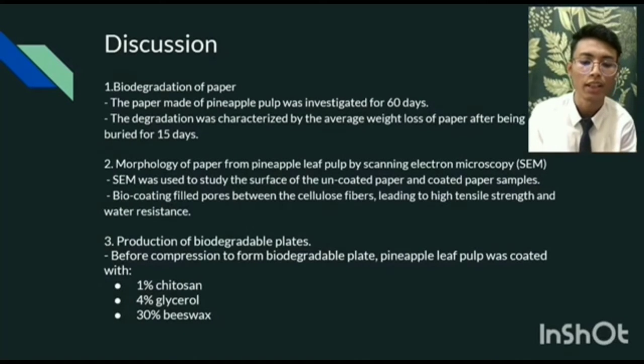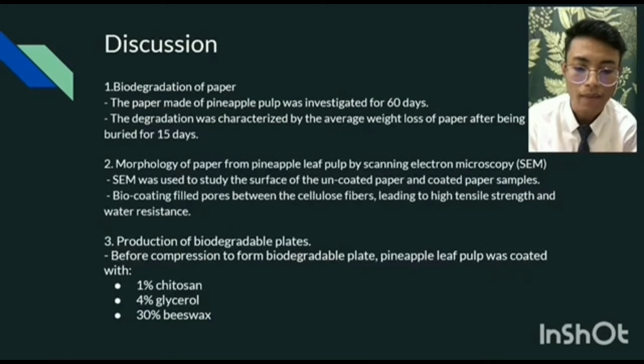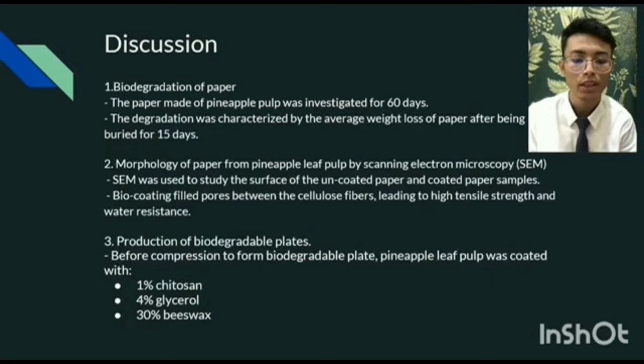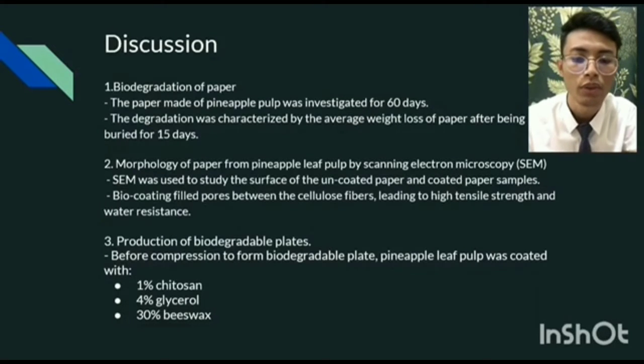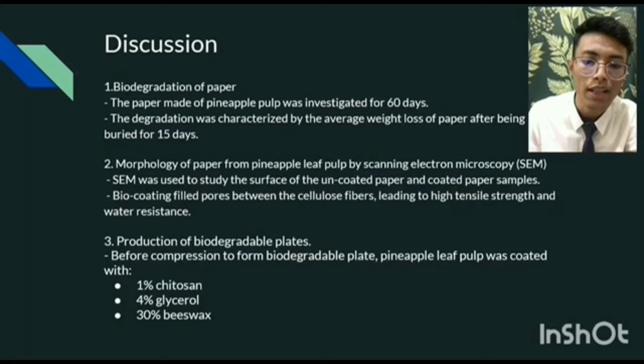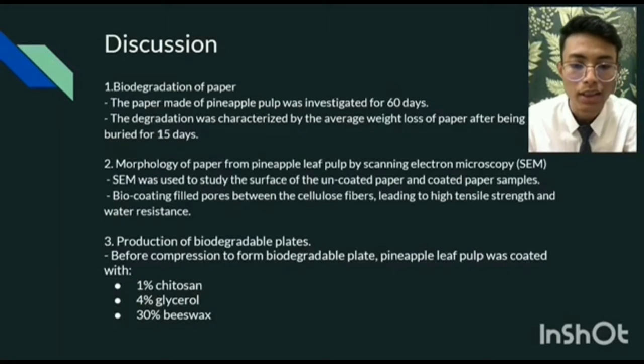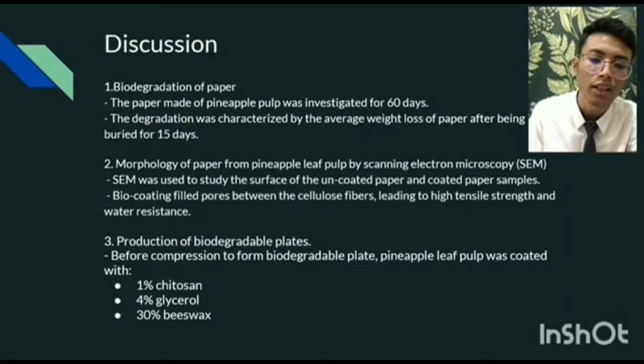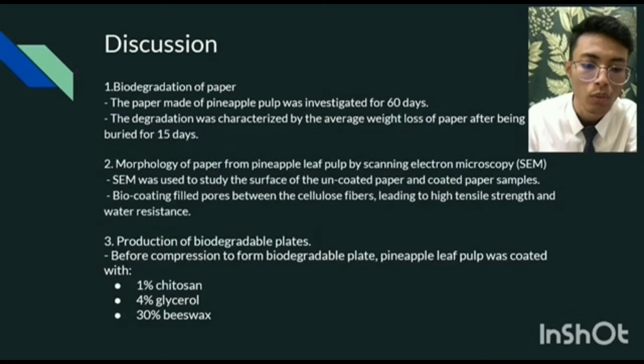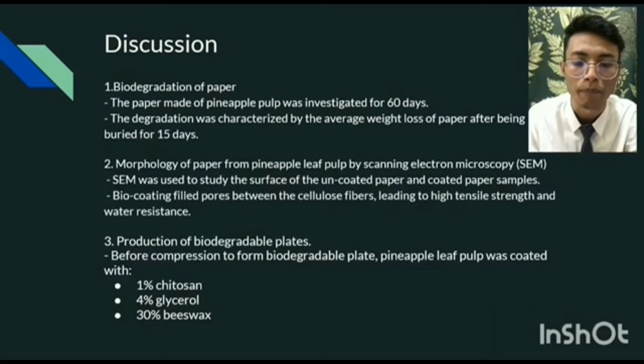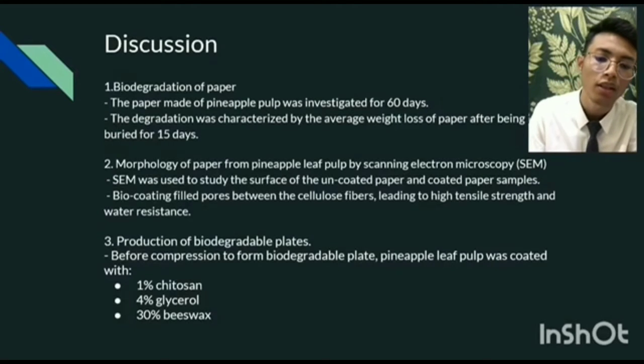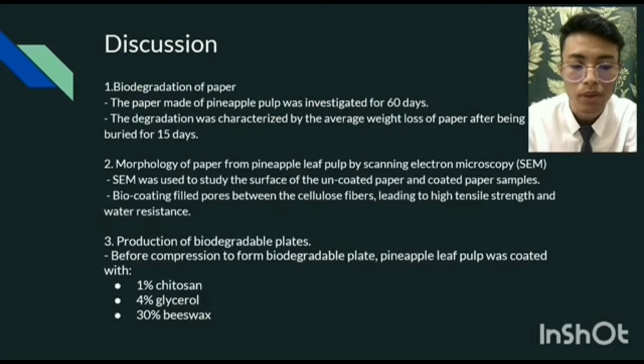Then they used scanning electron microscopy (SEM) to study the surface morphology of the uncoated and coated paper. The biocoating filled the space between the cellulose fibers, leading to high tensile strength and increased water resistance. Finally, in production of the biodegradable plate, the paper was coated with 1% of chitosan, 4% of glycerol, and 30% of beeswax before compression to form the biodegradable plate.